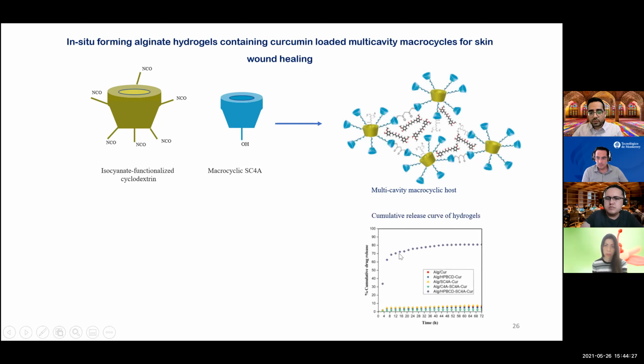And I put some results regarding the cumulative release curve related to the release of the curcumin. As you can see here, there are again different types of samples. There is the alginate curcumin, the alginate with only cyclodextrin, and the alginate with only a single host of the calixarene. The fourth one is the combination of the two different calixarenes, sulfonated and non-sulfonated, and the last one is the interaction between cyclodextrin and sulfonated calixarene.